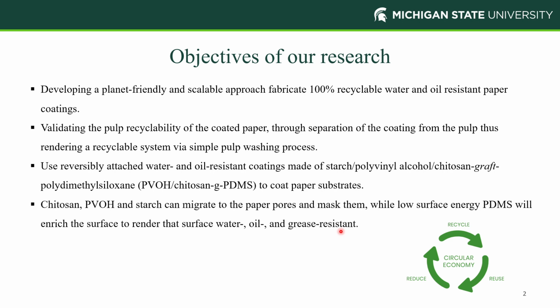And our hypothesis is that the chitosan, PVOH, and starch, being hydrophilic materials and very structurally similar to cellulose, would cover the pores of the paper, and the low surface energy PDMS would be enriched on the surface, which would produce the water and oil resistant paper.